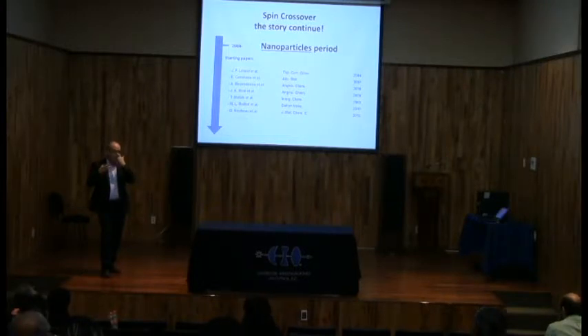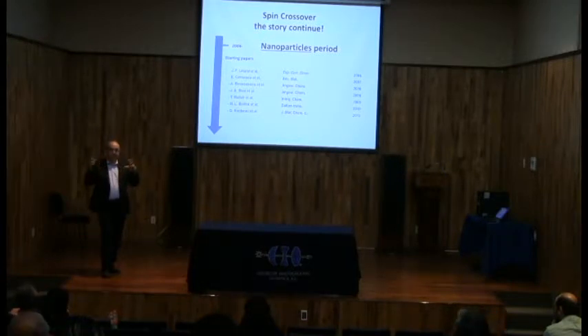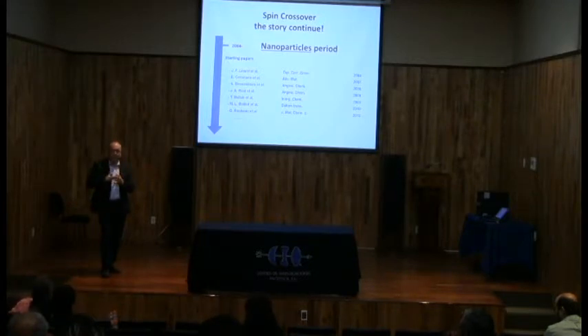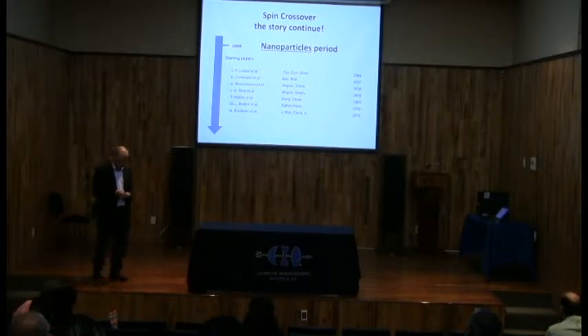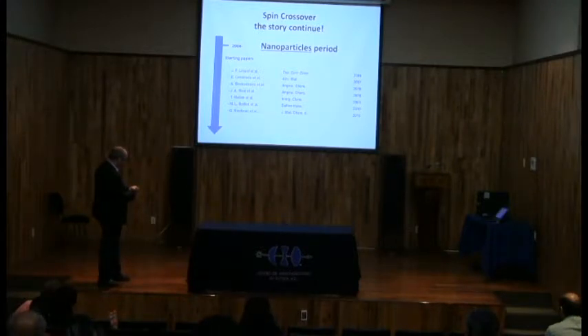Why? Because as I told you, the interaction between molecules is elastic. And then your coupling depends on the elasticity and also on the number of the neighbors. Okay? If you take, for example, a system where you decrease the size, you are looking to see what is the effect of reducing the size of the nanoparticles on these interactions and on the phenomenon. You expect then to go from a first order phase transition to just a gradual transition, and then we wanted to see this phenomenon experimentally. Okay, so the nanoparticle part.